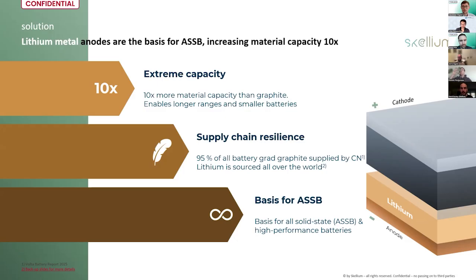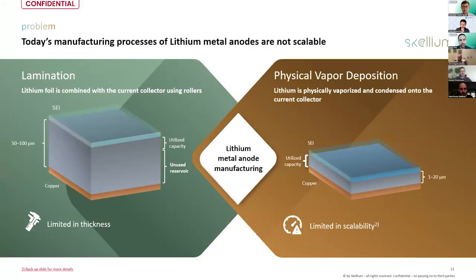Depends on how you want to frame it. What we actually do is we manufacture the lithium, but we cannot only use it for solid states. We can also use it in a different way due to our process. The current process right now to produce lithium metal electrodes is on the one hand, extrusion and lamination process, and on the other hand, it's a physical vapor deposition process. So we have, on the one hand, the very good commercial ready electrodes, but you have a thickness of 50 to 100 microns, and this is way more than you actually need. And on the other hand, you have the lithium metal, which is deposited by vapor, and you can imagine that the vapor deposition is very, very slow. So it's also limited in scalability.